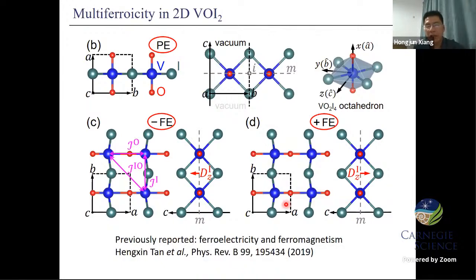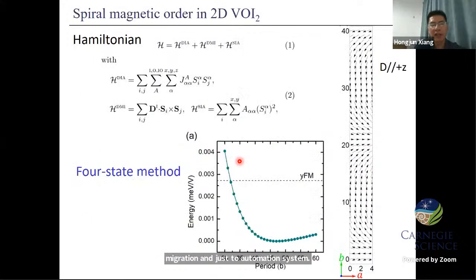And previously, actually, there are some studies. For example, this work predicted ferroelectricity and ferromagnetism in this two-dimensional system. But from our density functional calculations, combined with our first-principles method, we constructed the spin Hamiltonian, and we found that actually the ferromagnetic state is not the ground state, and the ground state is a spiral-like state, like this.